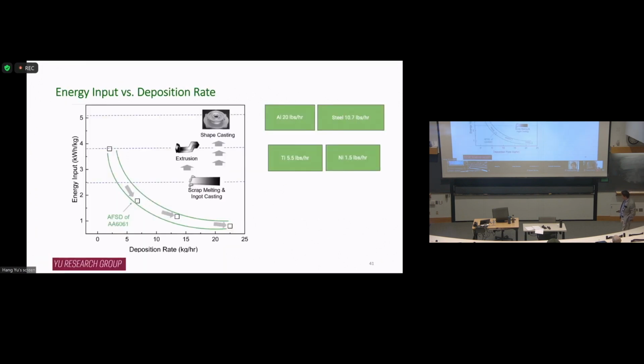The last thing I want to talk about is energy. It turns out energy input is relatively low. The vertical axis is essentially the energy cost per mass, in kWh per kilogram. If you have a relatively low deposition rate, you can be in a regime of 4 kWh per kilogram. But if you increase the deposition rate, you can lower the energy input per mass. That's very impressive compared to traditional manufacturing processes like ingot casting, extrusion, or shape casting. So this definitely gives us a low energy path toward a more sustainable future.